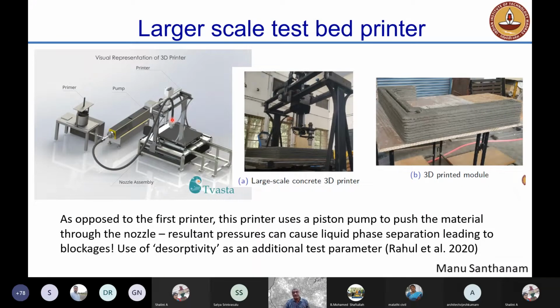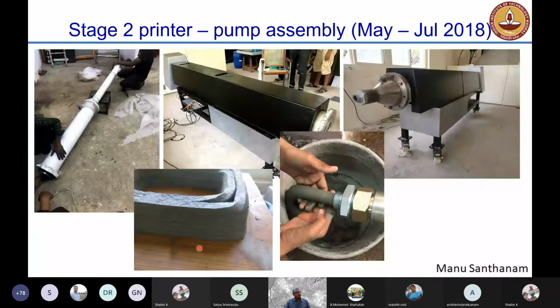So how do you ensure that that does not happen? You additionally add one more test, which is called the desorptivity test here. What we do is we basically take this concrete and put it inside a cell and apply pressure using a gas, and we see how much water bleeds out. Okay. Less the water bleeding out, the better the concrete is for this operation of pumping. You can see here the pumping being done, material is coming out nicely in a single flow.